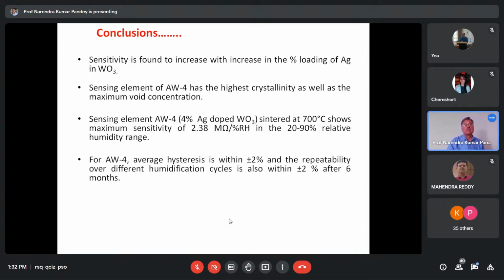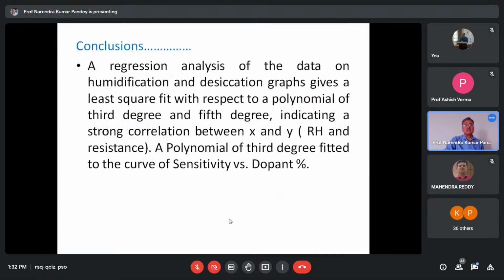You see, sensitivity is found to increase with increase in percentage loading of Ag. The sensing element of AW4 has the highest crystallinity as well as maximum void concentration. The sensing element of AW4, 4% Ag doped in WO3, annealed at 700 degrees Celsius, shows maximum sensitivity at this 4%. Average hysteresis is below plus minus 2%. Similarly, this was the regression analysis data that has been done.